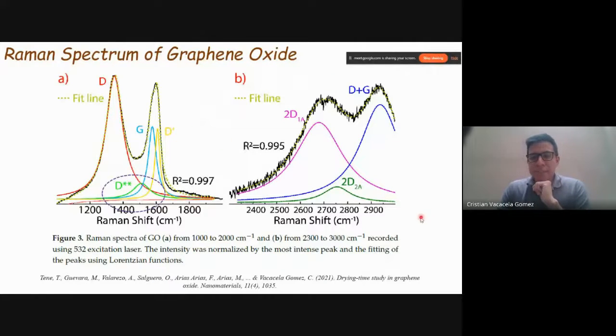But now, if we analyze the 2D band region, look at what happens here. If we remember, we have a different structure in graphite or few-layer graphene, but here we have an extra peak, the D plus G peak. If we fit all these peaks, we can see the 2D 1A, the 2D 2A, and now the extra D plus G band. So we have extra bands. That is why it is important to understand how these bands appear, and of course how we can modify and control them, or even exploit the presence of these bands for different applications.